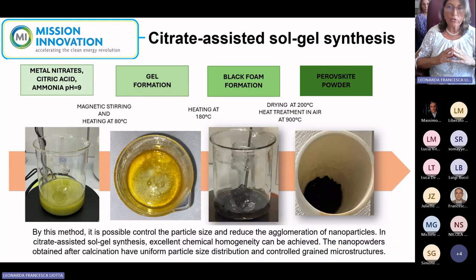And the other methodology starts also with citric acid. We have a solution, we have high pH, and of course the metal nitrates as a starting point. But the gel formation is slow, and then from the gel to the perovskite powder, we have a slow decomposition: first heating at 180, then drying at 200, and then the treatment at 900. So this slow transformation allows us to control very well the particle size, to reduce agglomeration of nanoparticles, and to obtain excellent chemical homogeneity, like is usually obtained in sol-gel methods.